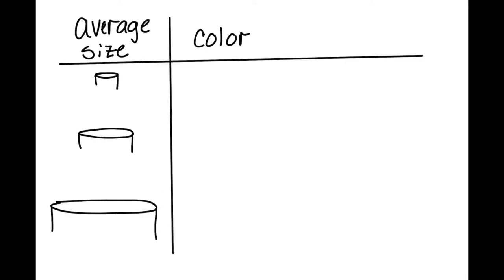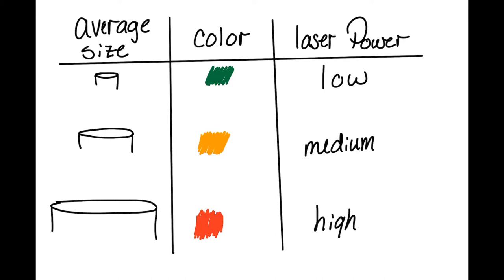The absorption spectra of the nanoparticles are dependent on the average size of the nanoparticles, so by changing the average size, we are able to shift the absorption spectra and tune the color of the light that we see when looking at the nanoparticles. In practice, by changing the exposure dose, which is the combination of the laser power and the scanning speed, we are able to change the size of the nanoparticles and thus the color.